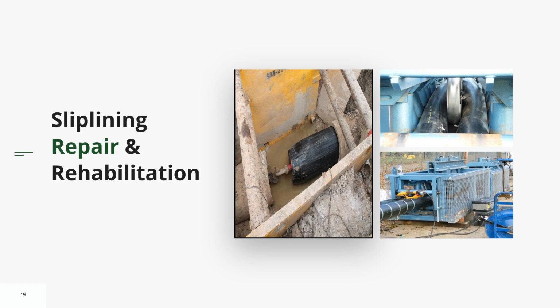There is another process that you can do where you can swage line. So you can actually pull high-density polyethylene, because again, high-density polyethylene has a great ability to elastically deform before it yields. So you can elastically deform the pipe, stretch it out, in other words. And so you're taking the diameter down by 10, 15, 20%, pull it into the host pipe, and then let it spring back, if you like. Now, it doesn't spring back as such.